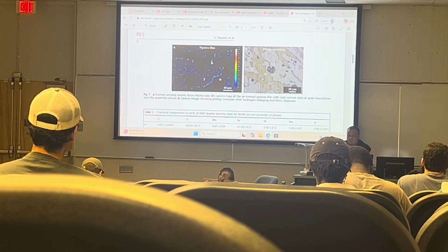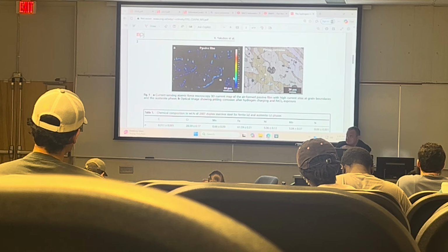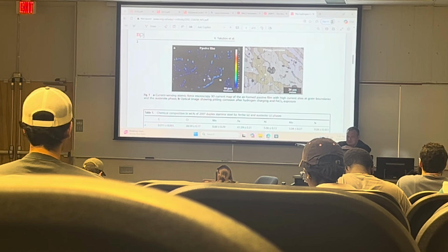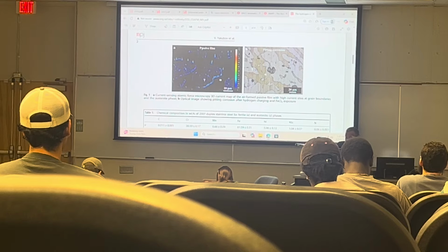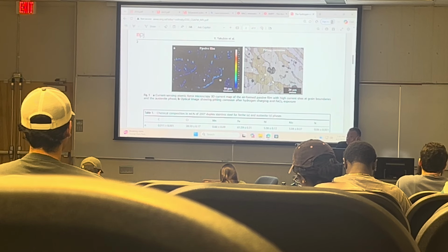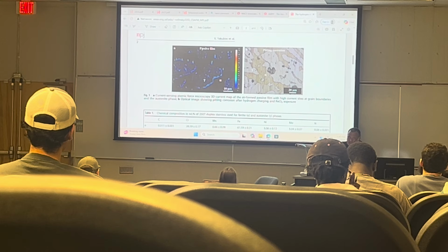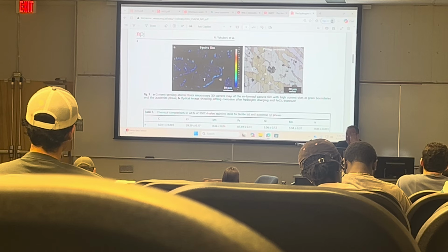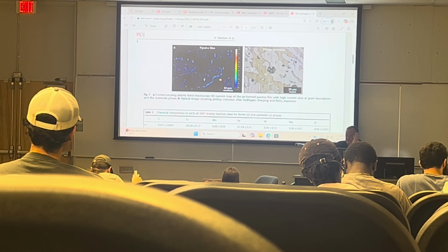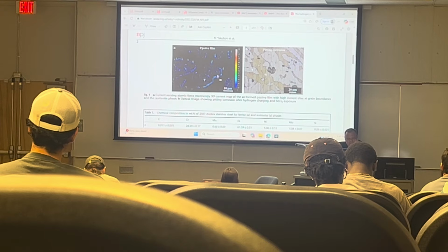And it turns out that the reason was, this is the current in nanoamps between the alpha and the gamma phase. And most of the current spikes you see are along the grain boundary. And this is the reason why even the passive film on the duplex, which means two phases, alpha and gamma. This is an awesome picture.